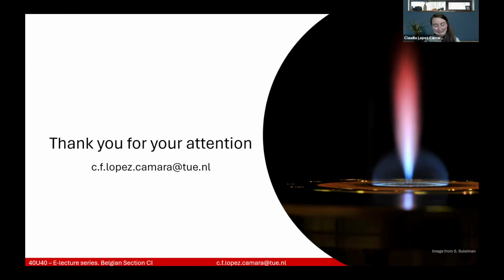Yes. Can you hear me? Yes, thank you. Hi, Claudia. Nice to see you. Thank you for this talk. Very interesting. I have a question regarding whether you saw a connection between the fact that you showed at some point, I think it was slide 14, that the diameter of your few-layer graphene would increase as you go higher above the nozzle, but at some point there is a decrease. There is a sampling point where you see a decrease, and I was wondering if this can be explained also by the fact that the graphene is burned somehow, the same as happens when you do the sintering of your particles afterwards outside, as you've shown in one other slide. So if there is a connection, or maybe these are two different mechanisms that occur.